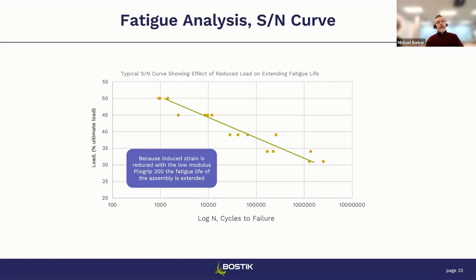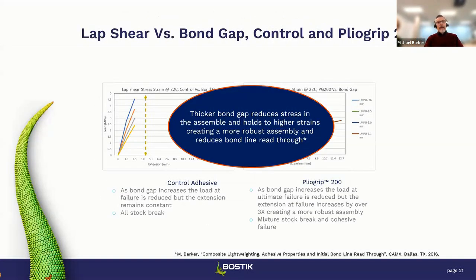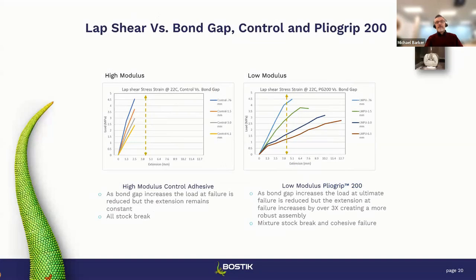Even though the strength is less with the low modulus adhesive, and I'll back up to that picture, you can see the stress in this case, with a lower or higher bond gap. Even though the strength is coming down, you're not going to reach the point of deformation, the catastrophic failure point of the low modulus adhesive, when it's driven by the expansion and contraction of the assembly.